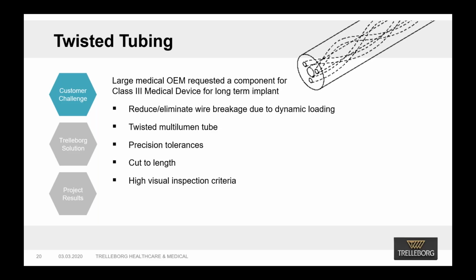The twisting process must be done without distorting the extrusion or creating visual defects. In this case, the extrusion was also cut to a short length with a precise tolerance and was sensitive to the risk of small visual defects that could become mechanical failures. Recognizing this device risk in the industry, Trelleborg had experimented with methods of creating twisted extrusions prior, beginning with twisting of short lengths.